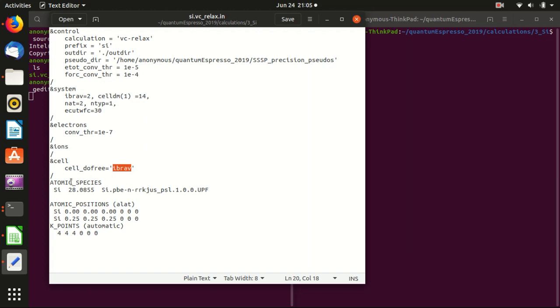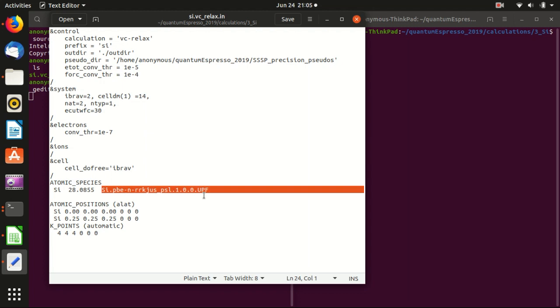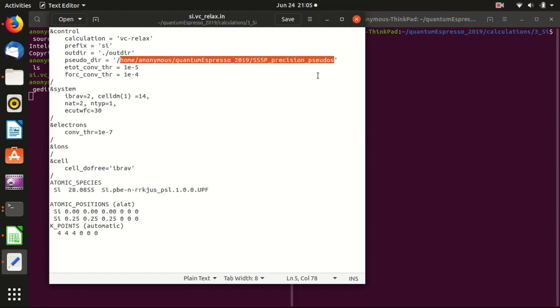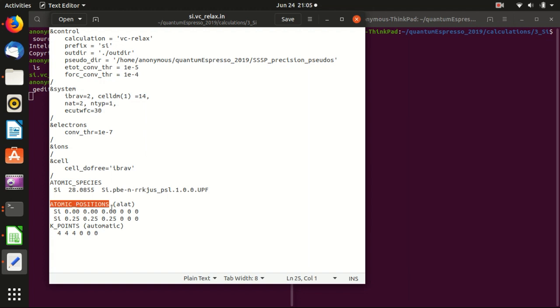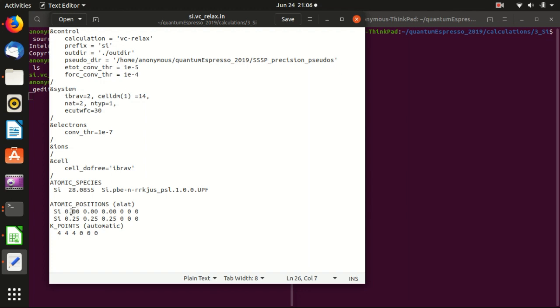And then the atomic species silicon and atomic mass of silicon. And this is the name of the potential file from the SSSP library that you can find in this directory. And the atomic positions, like this time, we don't use Angstrom. We use alat because this is more convenient in this case, in the case of crystal. We know that for silicon crystal, it is basically two FCC lattices shifted by one fourth of the crystal of the unit cell.